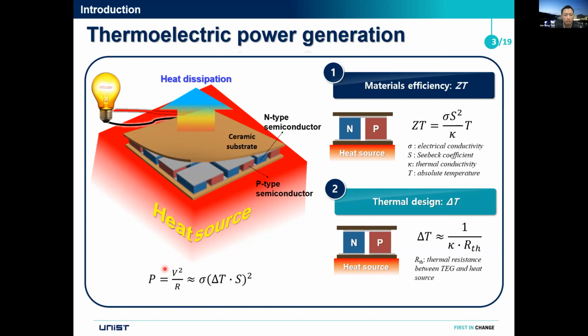So we can say that this power can be determined by two important parameters. The first one is the material efficiency, the so-called ZT value. ZT depends on three different parameters: electrical conductivity, Seebeck coefficient, and thermal conductivity. These three parameters are strongly correlated, so it's very difficult to increase the ZT value. So many people have focused on the development of efficient thermoelectric materials with high ZT value so far.